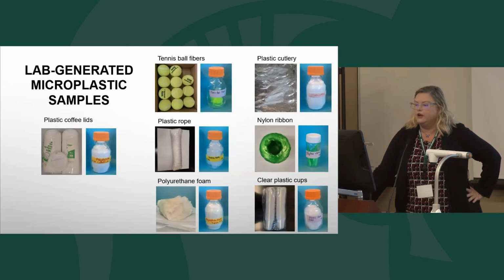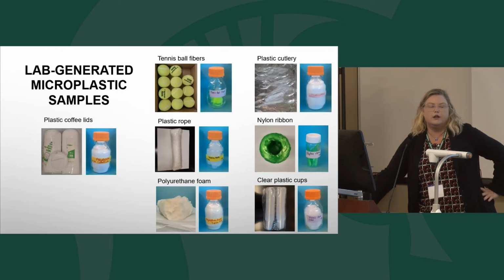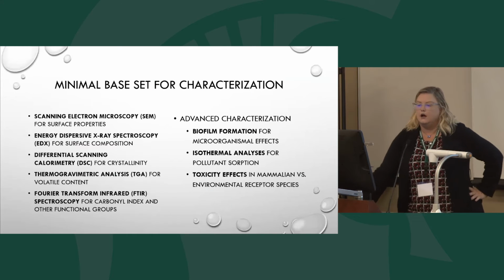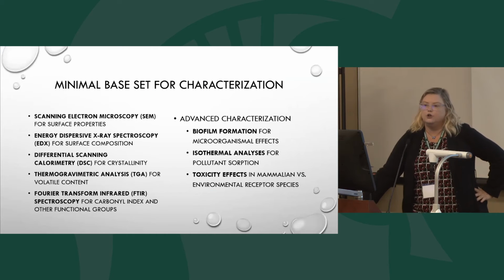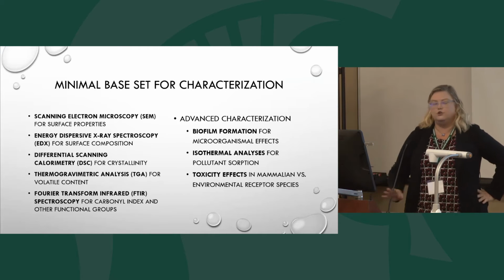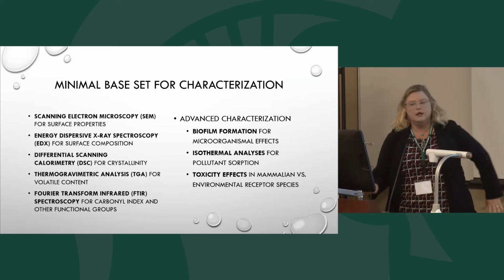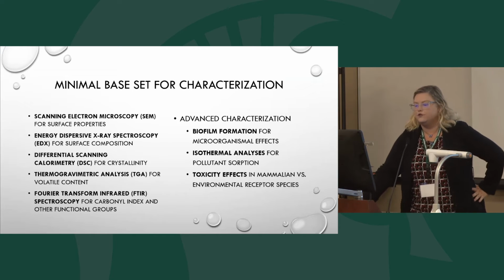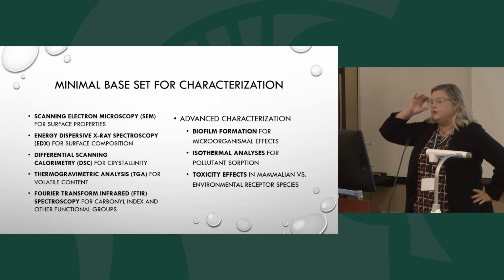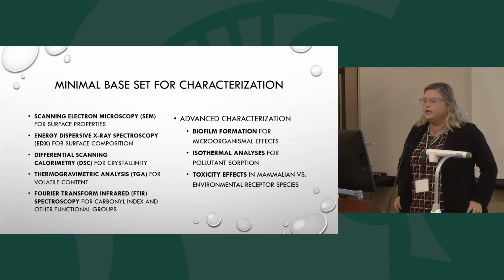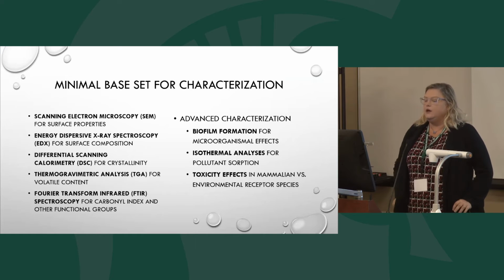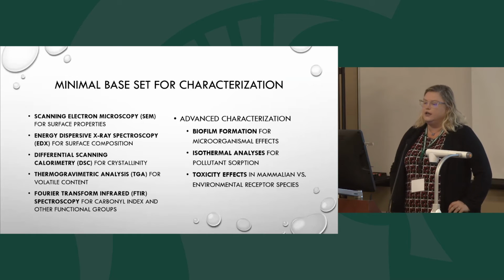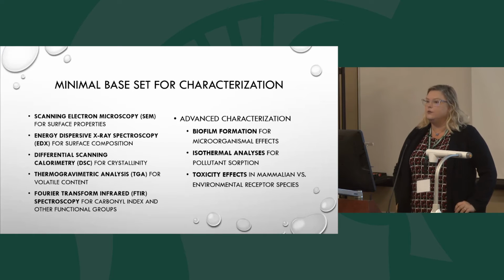So the minimum base set for characterization that we're using for each one of these particular plastics, and what my grad students and I are looking for whenever we're reviewing papers that are published in the literature, are these 5 things over to the left-hand side: scanning electron microscopy for the surface properties. That's connected with the energy dispersive X-ray spectroscopy to get the surface composition. Then we're taking it to the brand new differential scanning calorimeter, DSC, to understand the crystallinity of the different microplastics.